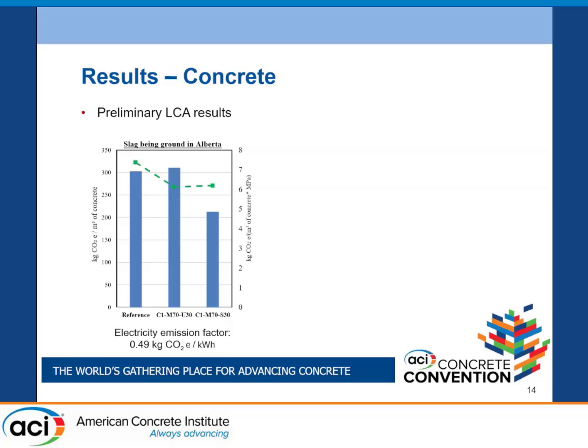Preliminary LCA results. We first did the LCA for Alberta, and the emission factor for electricity in Alberta is a little high. So that's why our concrete with ultrafine slag and metakaolin doesn't show any decrease in GHG emission per cubic meter of the concrete. But if we normalize the results to the compressive strength, the GHG emission per cubic meter multiplied by MPa, we almost see a comparable number between the slag and the sample with the UFS.